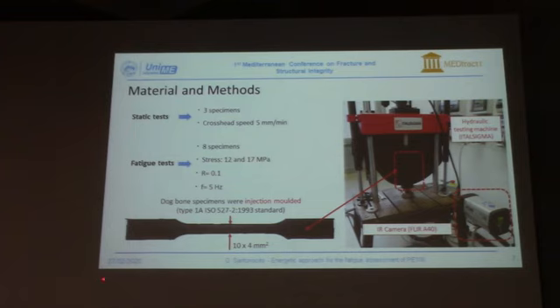For this experimental campaign, we adopted a hydraulic testing machine of 25 kN and an infrared camera FLIR A40. We adopted specimens made of polyethylene obtained by injection molding, adopting the geometry prescribed by the ISO standard. And we made two different campaigns. The first is a static test campaign, adopting 3 specimens with a speed of 5 mm per minute, while the second is a fatigue test campaign with 8 specimens and stress levels from 12 to 17 megapascal, a load ratio of 0.1 and a frequency of 5 Hz.